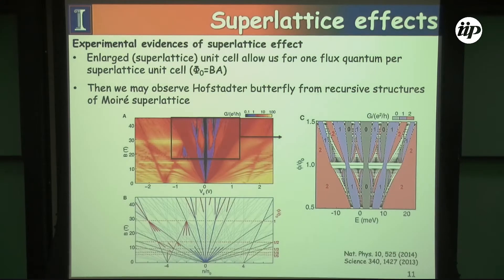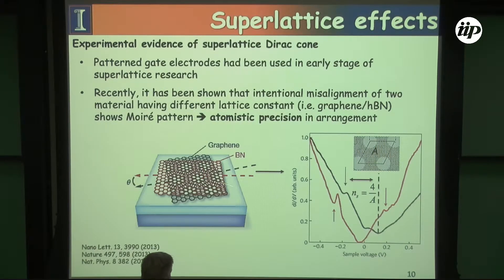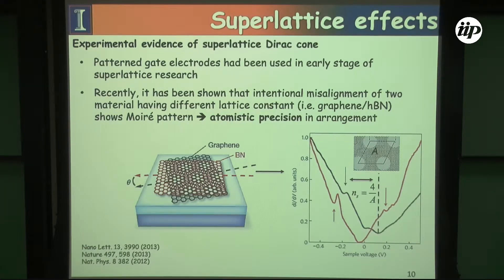One such interesting thing is looking for the Hofstadter butterfly — the self-similar relationship in the Diophantine equation — where we apply a magnetic field and look at the calculated Hofstadter butterfly. There's a big effect of having graphene on boron nitride: you see a large difference between the electron and hole sides, because next-nearest-neighbor coupling between the graphene and boron nitride introduces an electrostatic potential that breaks particle-hole symmetry. This is why you get the asymmetric pattern.